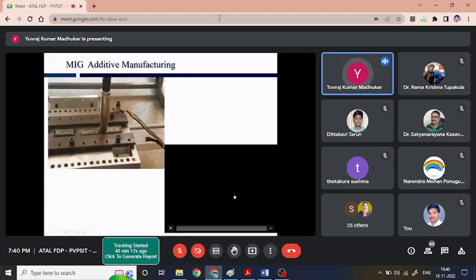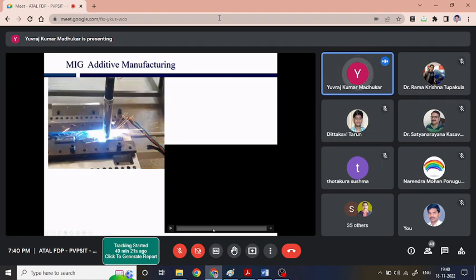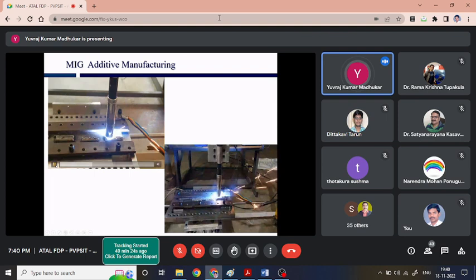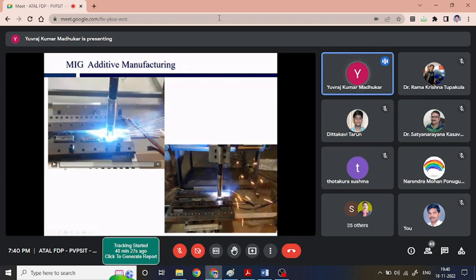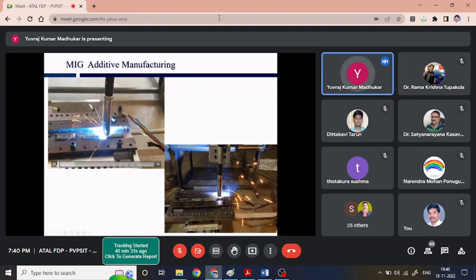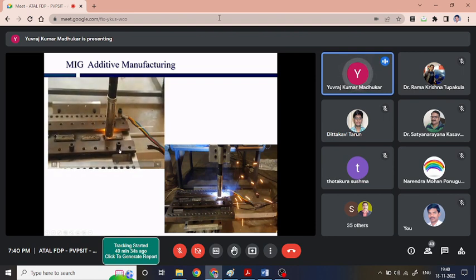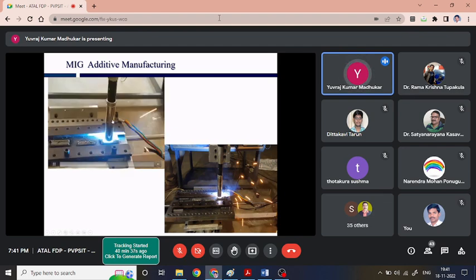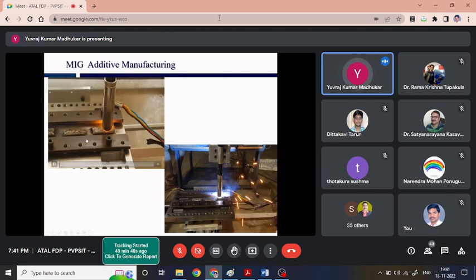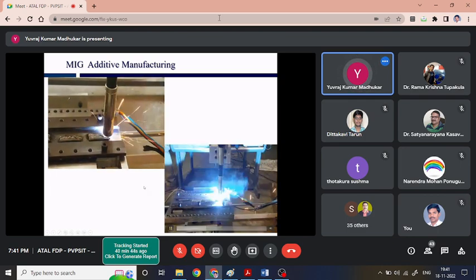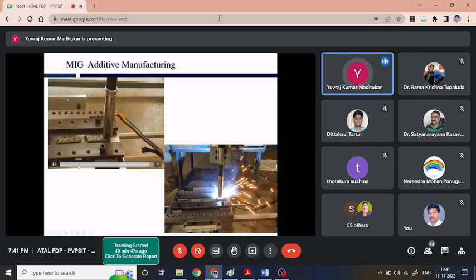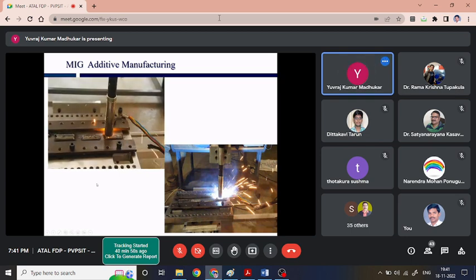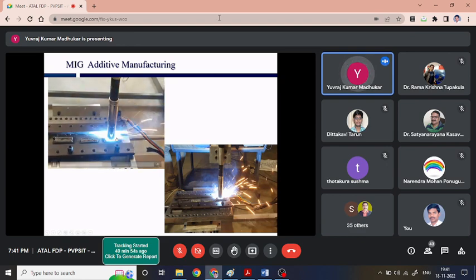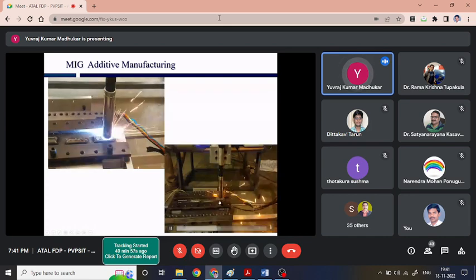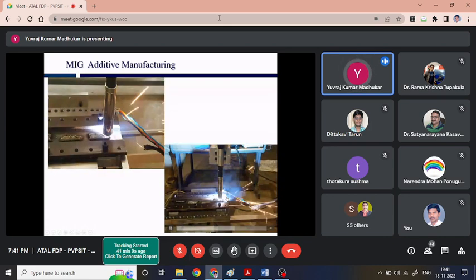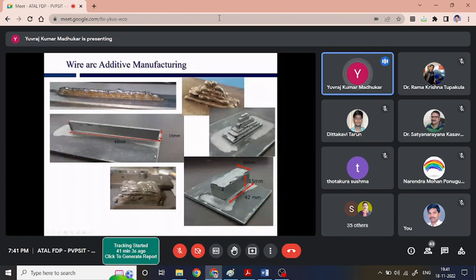So this is some of the videos we recorded during the deposition. The motivation behind showing this video is that at the beginning, while we're starting the process, we need to optimize the deposition parameters. It's a very complex process. The wire feeding speed and the speed at which the stage is moving need to be optimized. In the first video we could see that sometimes the arc is getting off during the process itself. Here we could see the arc does not remain consistent. It is getting off during the process compared to the other process, which is almost continuous. Actually, all these things affect the part quality that we are depositing.